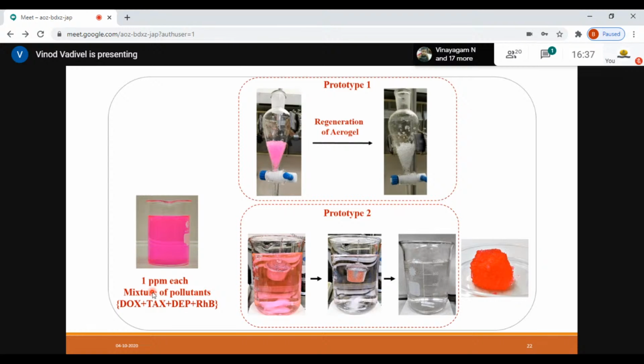So when you have this system of 1 ppm each, we tried with a colorant, which is rhodamine B, and the pollutants, the chemotherapeutic drugs, all together. We just poured them into this system. You can see it completely removes them from the aerogel, and this aerogel can be regenerated using ethanol.